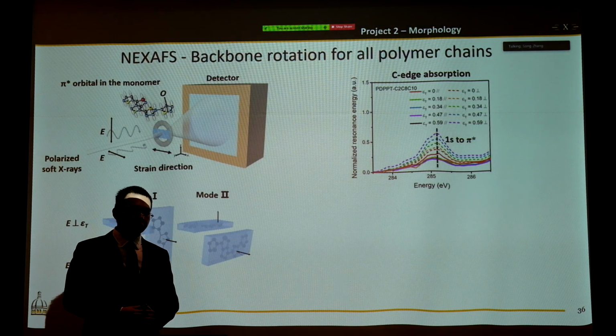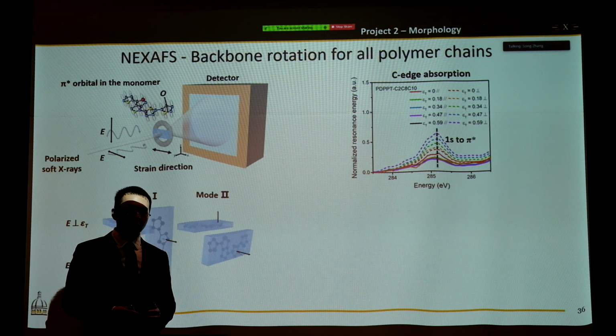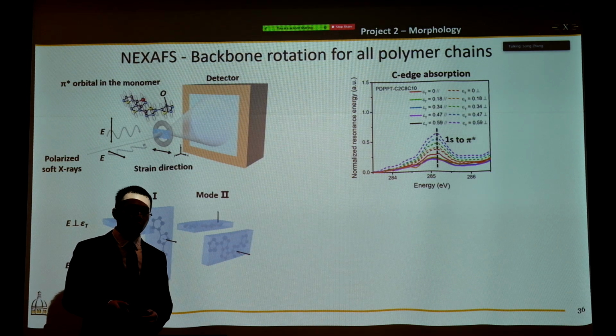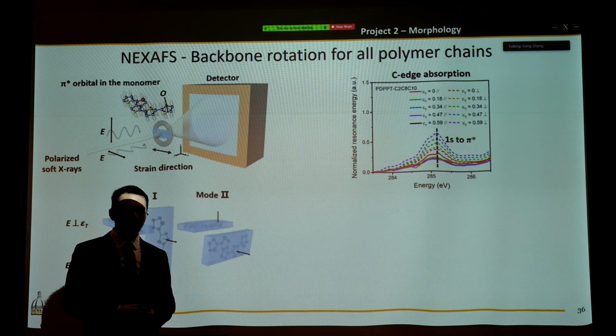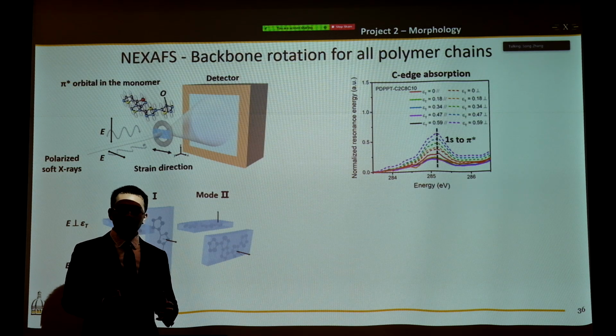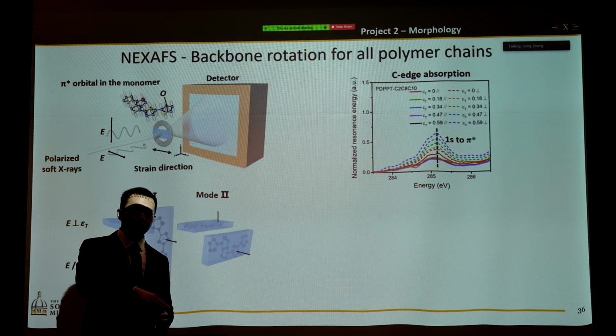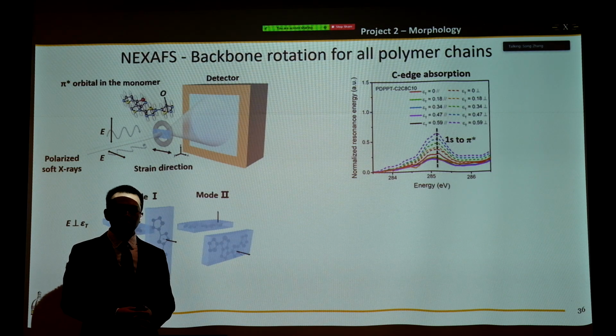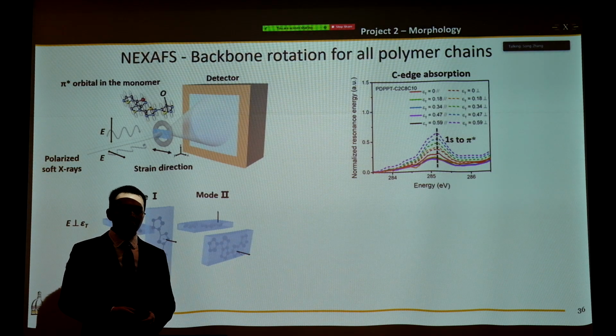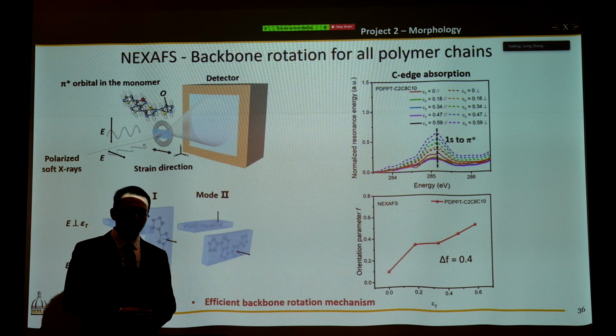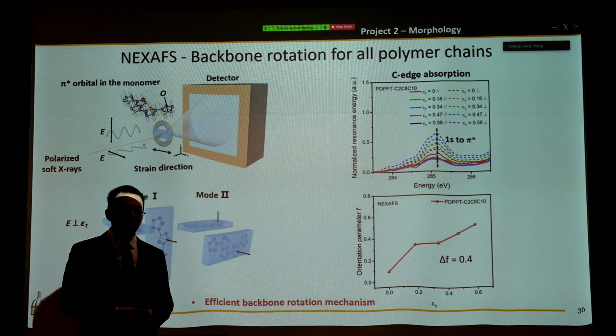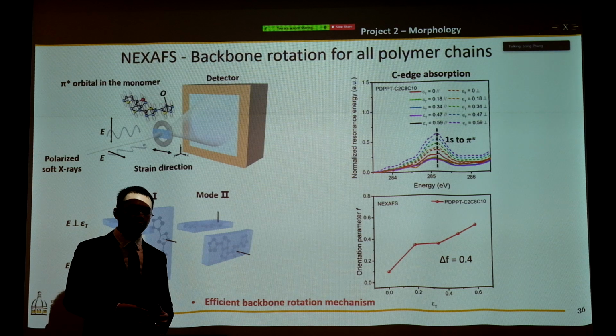Okay, now the third observation we make is the backbone rotation mechanism. And NEXAFS helps us to look at the absorption orbital for the 1s to pi star orbital. So basically, we are looking at the following two modes of rotation, mode 1 and mode 2 here, where mode 1 means your polymer backbone is rotating from vertical to horizontal, and mode 2 is simply a flip. The delta F value for this mechanism is equal to 0.4, which means it's very efficient in the thin film deformation.